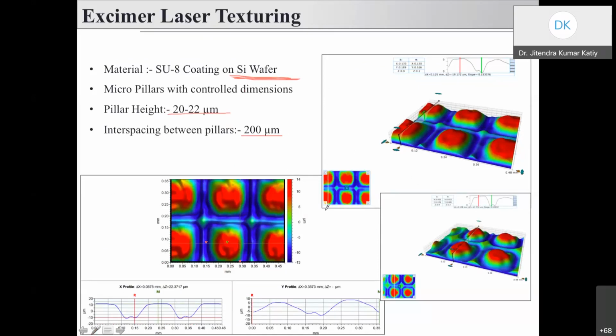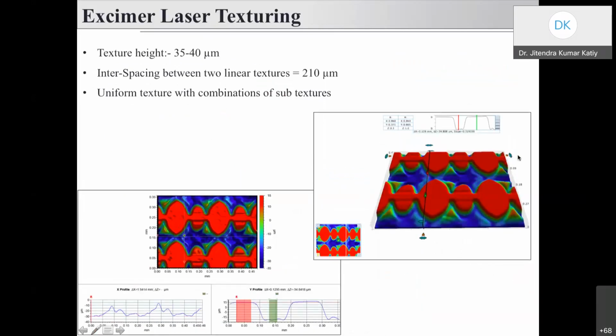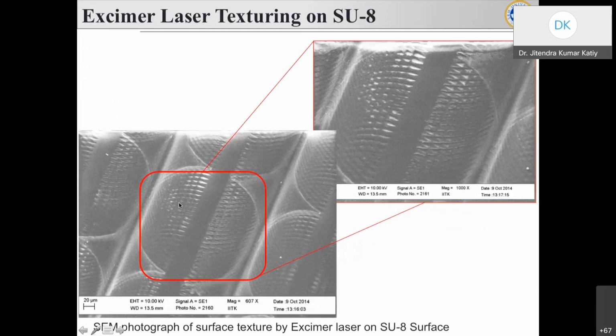texturing. Another beautiful thing when we talk about this texturing is what we observe in the SEM, which is very important. Uniform textures with a combination of subtextures are observed in this texturing. This is a shark-type phenomenon. You can see the very beautiful shark skin image; shark skin surfaces look like that. The textures we have developed are very beautifully covered with that shark skin. So it can reduce friction and wear in an excellent manner.